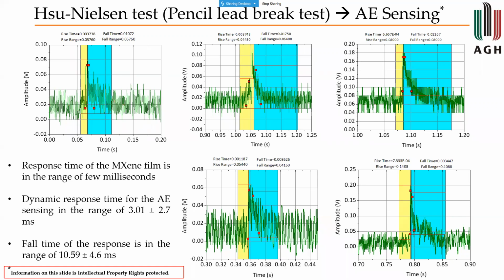And in this process, we found the response time and the fall times to be really promising in the range of milliseconds. But it also requires us to characterize the material, the piezoelectric coefficients, and see how they could be related to the theoretical values and the propagation of wave that happens through the medium.